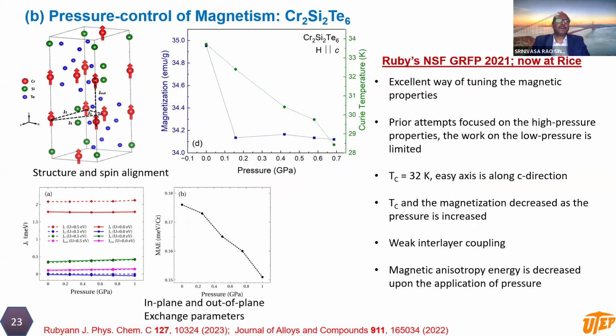And moving on, we also applied pressure on these layered magnets, and we varied the pressure, particularly in the low pressure range from 0 to 1 gigapascal. That's what we have in our group. We observed that the Curie temperature decreased and the magnetization decreased as a function of increasing pressure. These measurements were complemented by theoretical calculations, and as you can see, the magnetic anisotropy energy changes as a function of pressure.